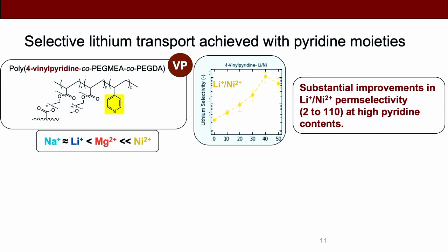So this is a 4-vinyl pyridine pendant group here. And what I'm showing you is lithium selectivity versus nickel. So this, again, is not the hardest separation we could do. There are commercial membranes that could do this. However, we're able to do the selectivity on the order of 100, right? So for every nickel that goes across, we can get 100 lithium ions to go across. Commercial membranes can't do that, but they do it on the order of more like 30.